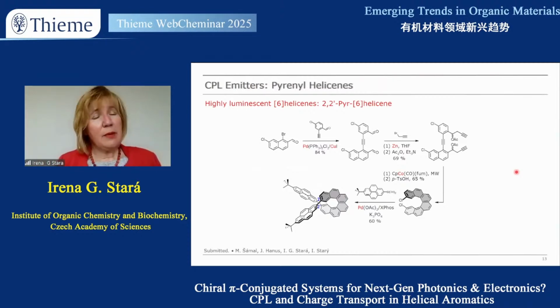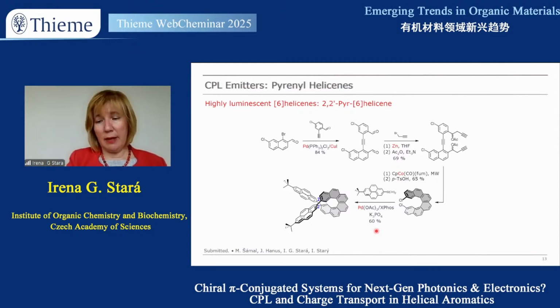We went further and looked at some other compound design, not the design in which pyrenes are directly incorporated into the helicene backbone, which I just described, but a simpler model in which the helicene backbone has two sigma bonds carrying these pyrenes as substituents. Here is the synthesis in a nutshell, and you can see that the pyrene units are introduced at the very last step of the synthesis. We prepared a whole range of these pyrenyl-based helicene emitters, and I will just show you this one, C2 symmetric.